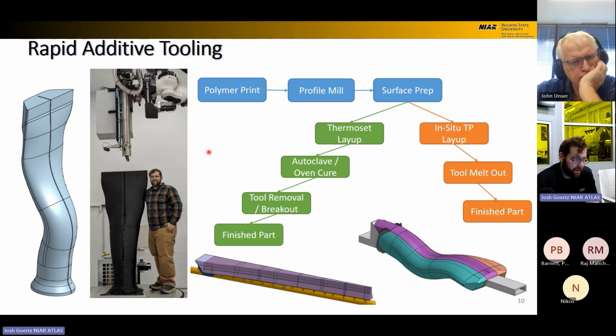get the surface finish you want, we'll be able to do a low temperature thermoset material cure on there, and then we can actually submerge that entire ABS print in an acetone bath and melt the tooling out of the part. Some of the other options we have include PVA, where we can do a water soluble tool so we can avoid the acetone mess.